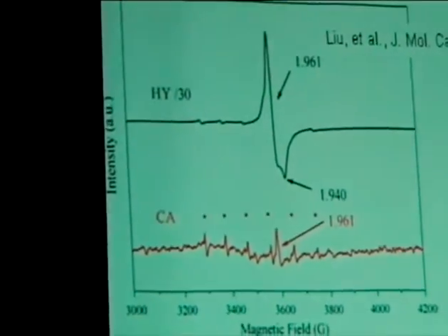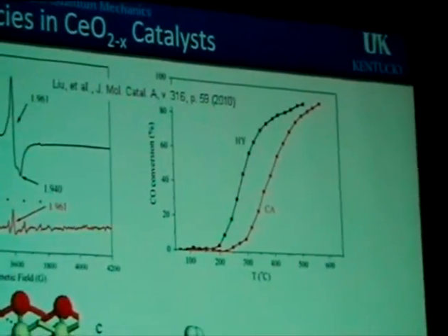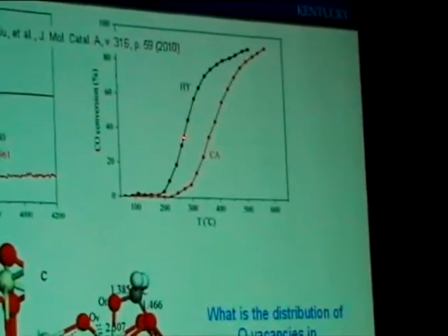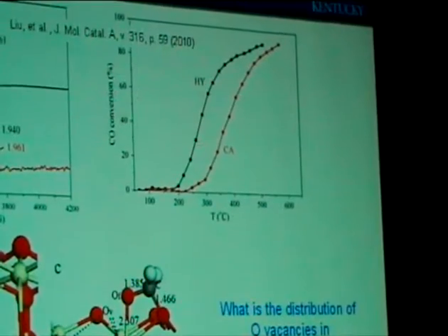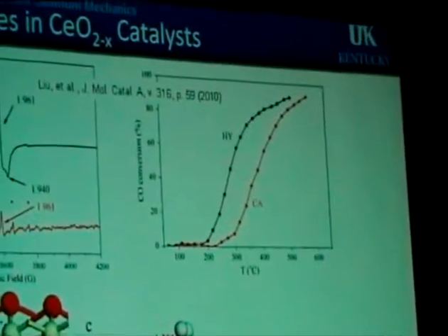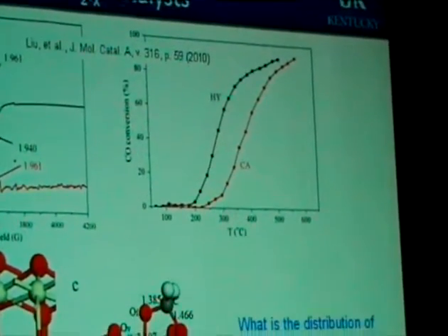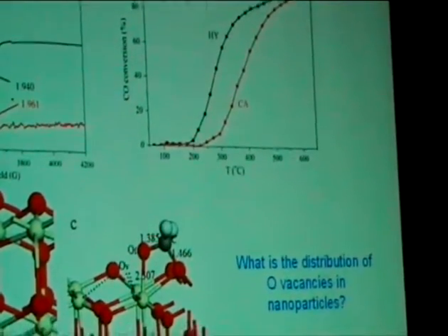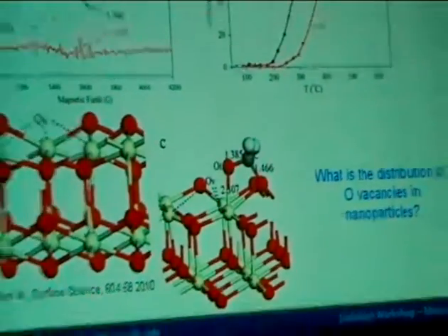And when you translate that directly into catalytic activity here in a carbon monoxide application, you see that it's this structure that has much higher conversion rates and higher activity. The point is, oxygen vacancies are somehow connected to catalytic activity. And there's been a lot of computational work on that, but nearly all of it has focused on, as a question to Alan hinted, specific arrangements of oxygen vacancies.